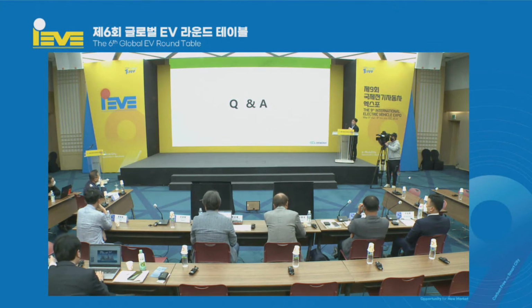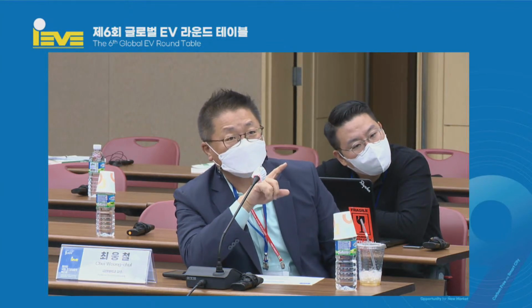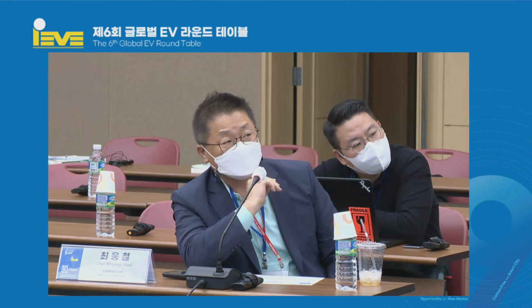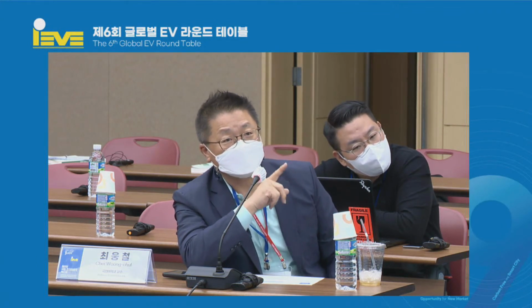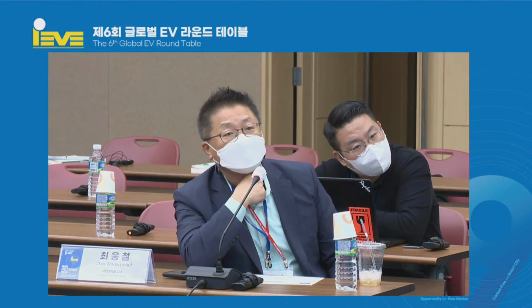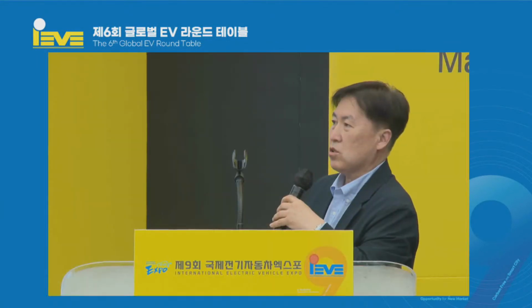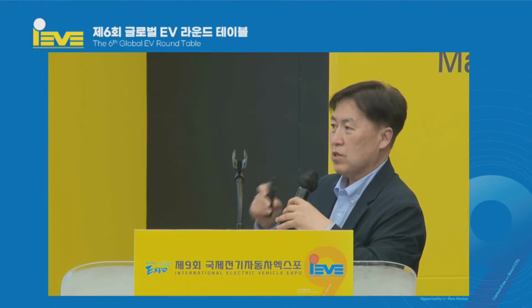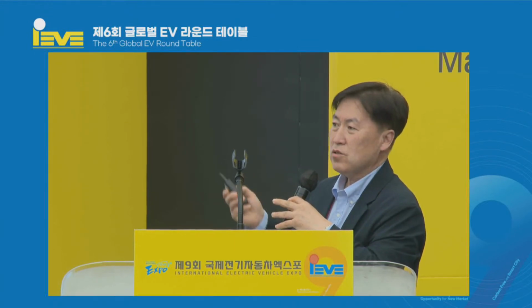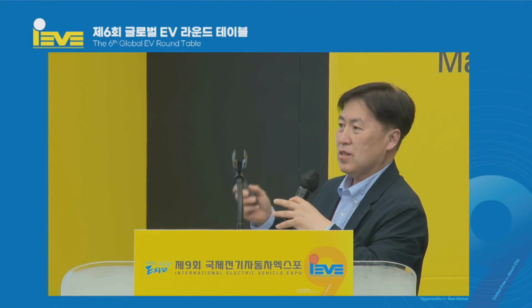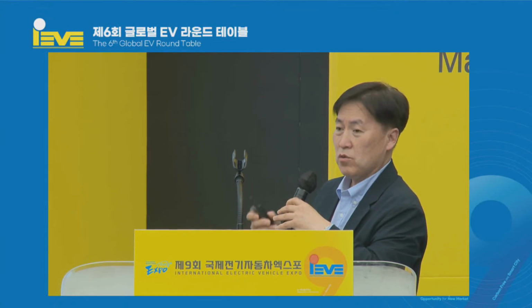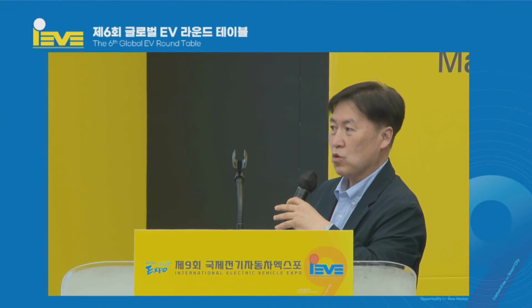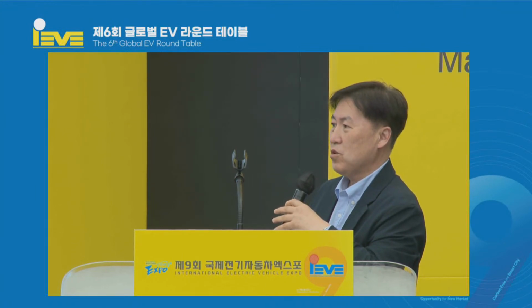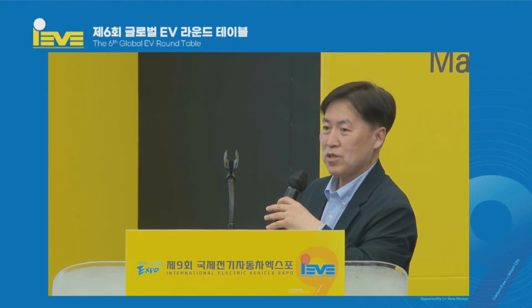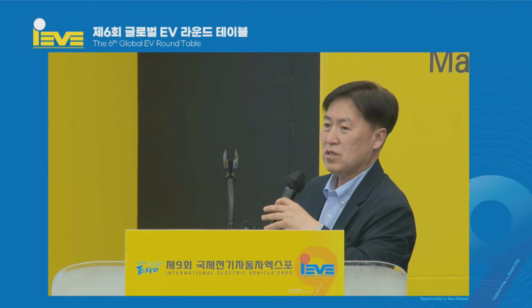Well, compared to other solid electrolytes, your idea is that it's based on gel type. So comparatively speaking, for the interface contact, you are in a better position because it's gel based. Yes, you're right. If we use a solid high polymer, we can totally separate it, but because this is a low polymer, low molecule, the issue of the interface can be much lower.